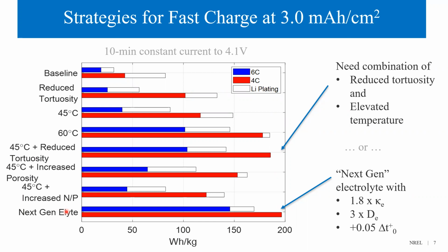Next generation electrolyte with 1.8 times ionic conductivity, 3 times diffusivity, and increased transference number is predicted to enable good extreme fast charging performance for high loading cells.